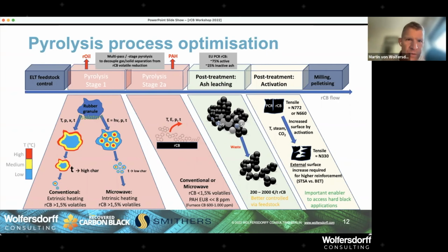And one important point, which was confirmed by Pirelli, is that when you put a powder in a rubber mixing mill, a Banbury internal mixer, typically during the mixing process there is a development of gases, and they need to open the mixer to let the gas out. Now, if you put the powder recovered carbon black in there, and the powder is not completely wetted and already in the rubber polymer, we risk that with the degassing, some of the recovered carbon black powder goes out of the mixer.